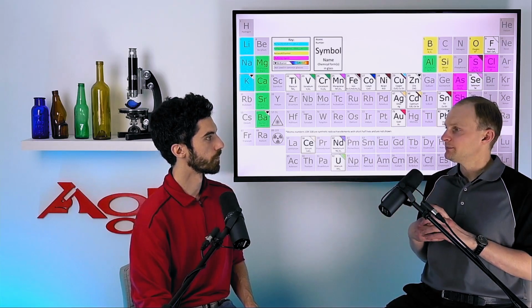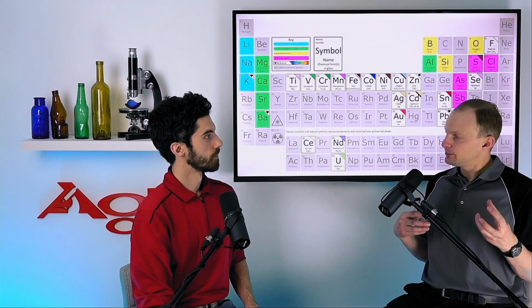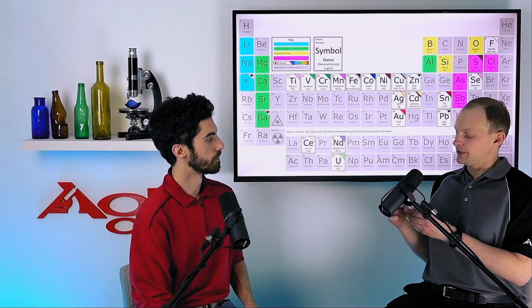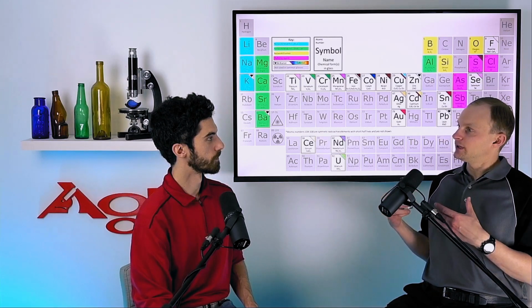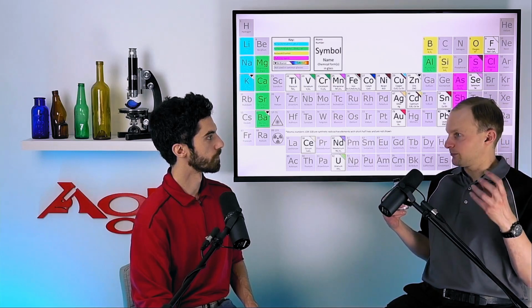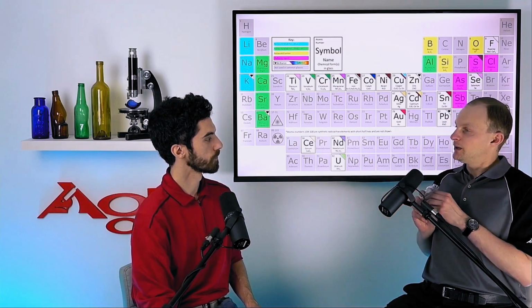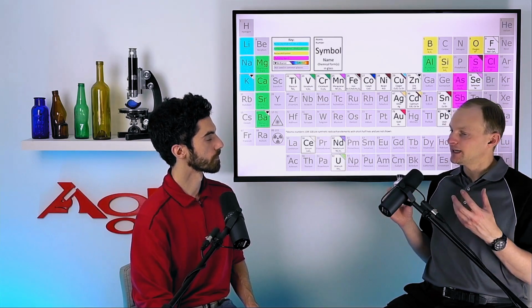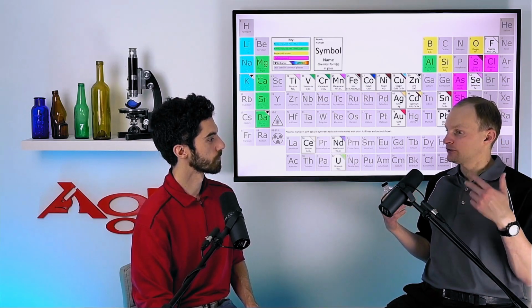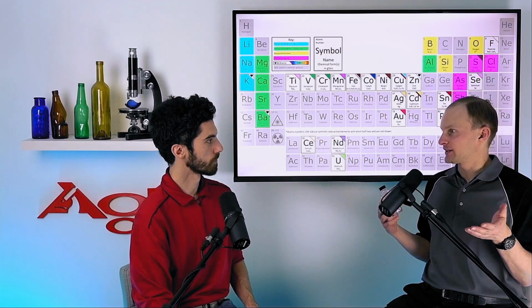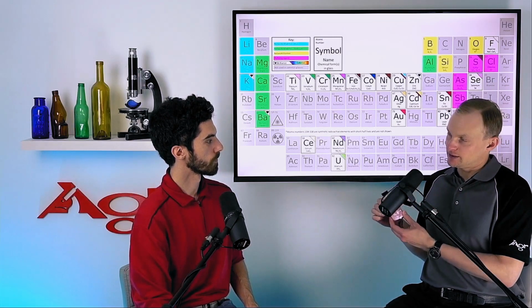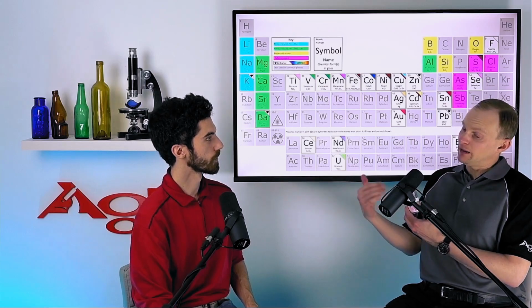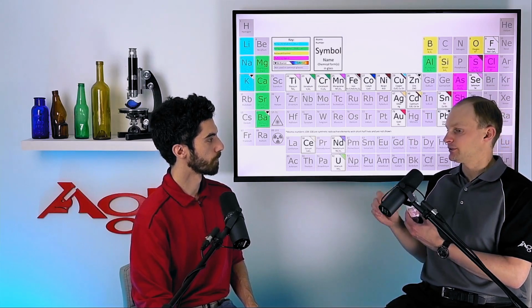But if we want to make much higher transparency glass, a higher end product, we can use something like erbium. So instead of using selenium to get our pink color, we use erbium, which has a tighter transmittance. We don't have to add as much, and so we're going to have higher clarity, higher transmittance of that object. The erbium will give us a pink color, and that's going to help balance out any green that's present from that iron impurity.